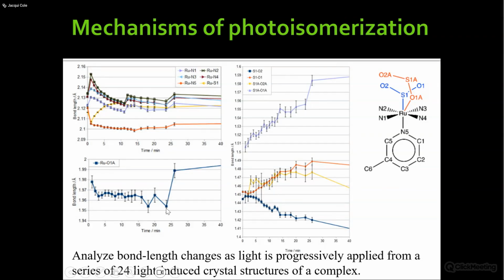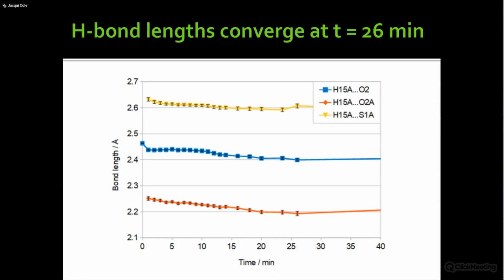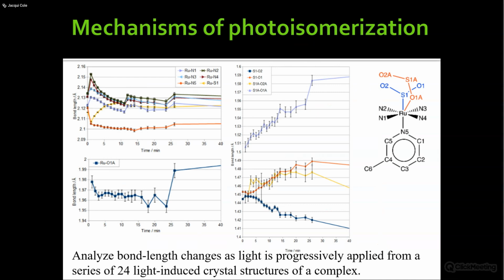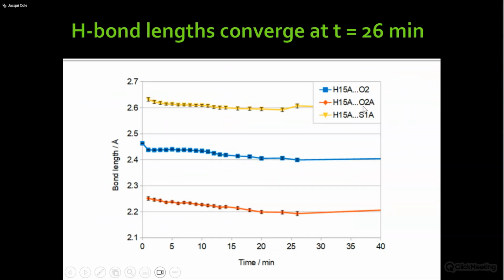So we then see this strange thing at 26 minutes, which we know is something to do with the oxygen-bound sulfur dioxide that's formed as a photoisomer. And again, remembering all this is happening in the single crystal state, the only thing you see changing differently, aside from this bond distance from the oxygen coordination to the ruthenium, is the hydrogen of one of the arenes, that's the one that's moving to alleviate the steric strain. That's the oxygen, and then the sulfur.